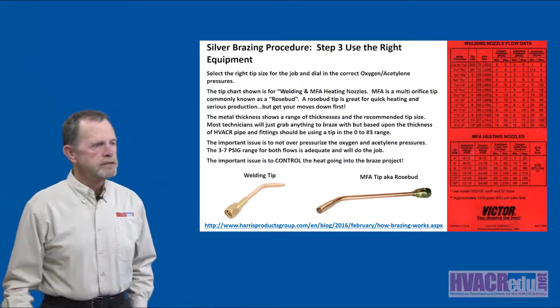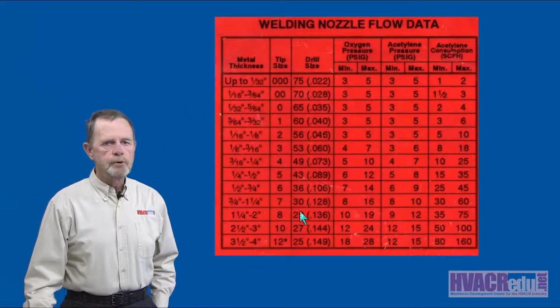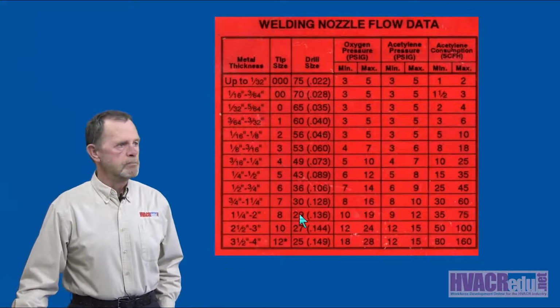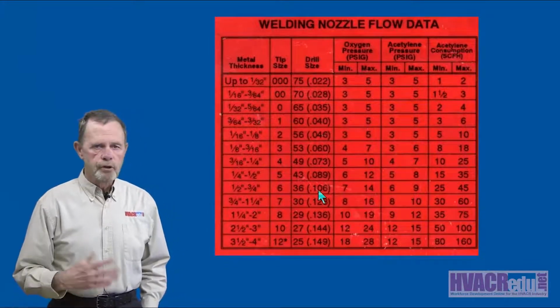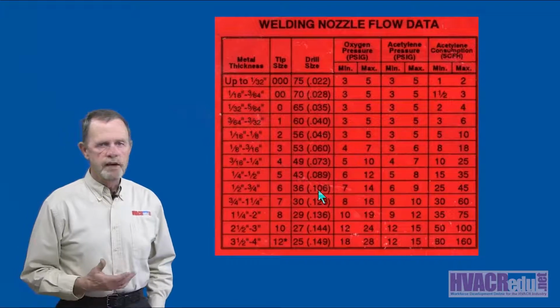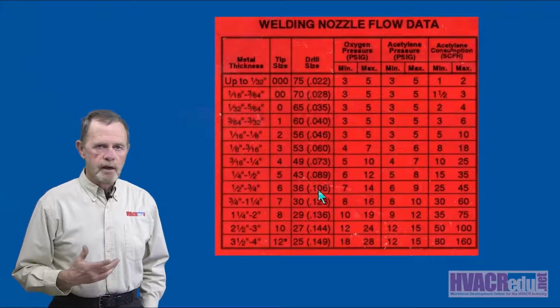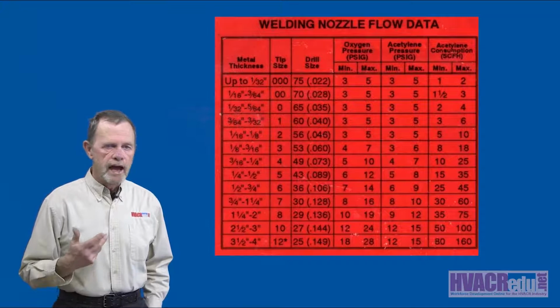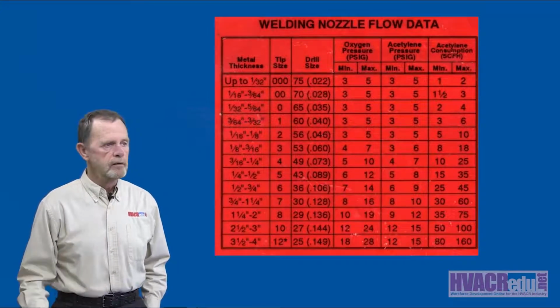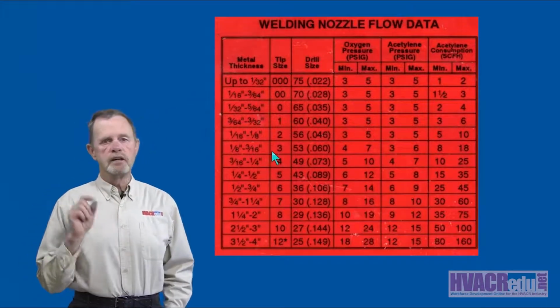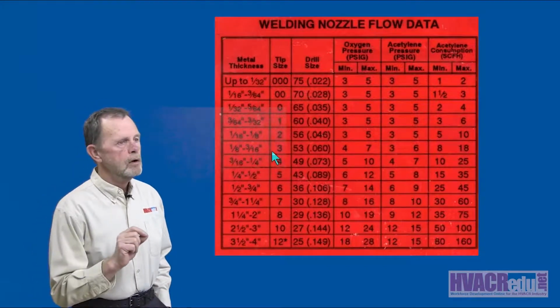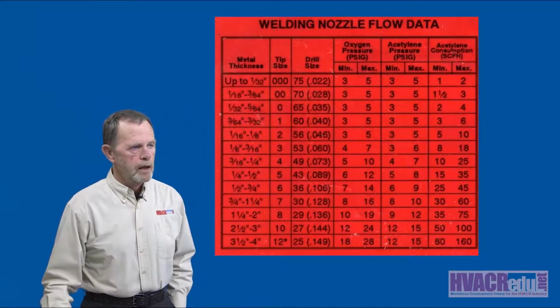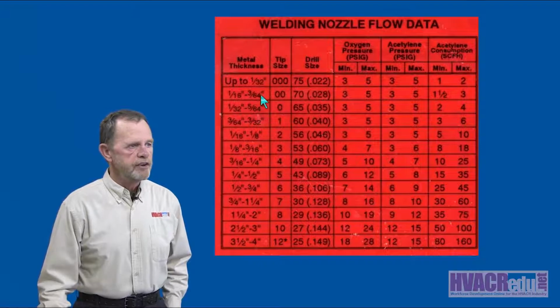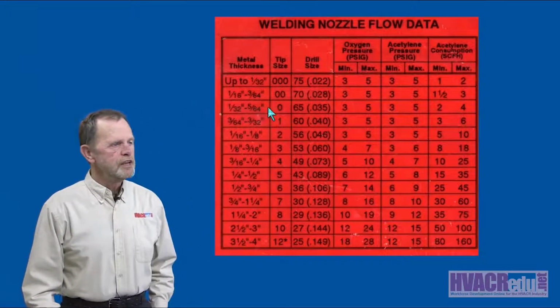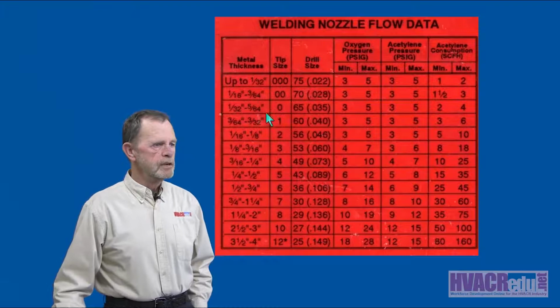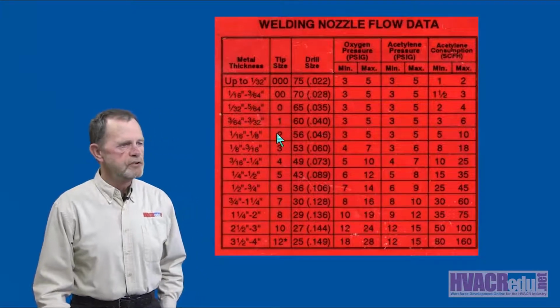What we have on the right-hand side here, if you stop at your local welding supply house, they will probably have tip charts. I'm a fan of tip charts because they give you the actual accurate pressures to dial in. They give you a tip size based on the metal thickness that you are brazing or soldering. And as you can see, metal thickness here, most of the stuff that you're going to braze in copper is going to be between this tip size of 0 to number 3.